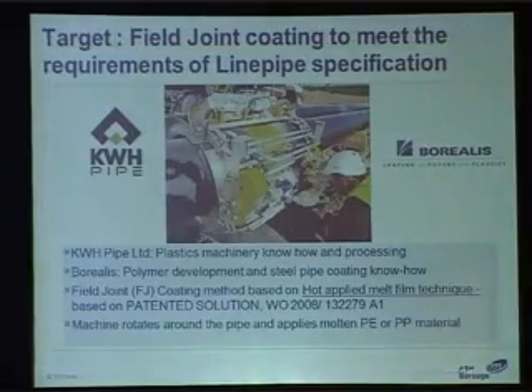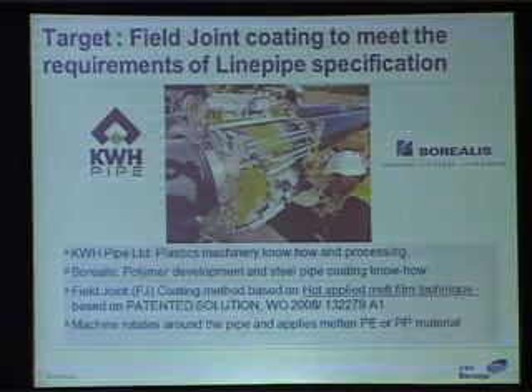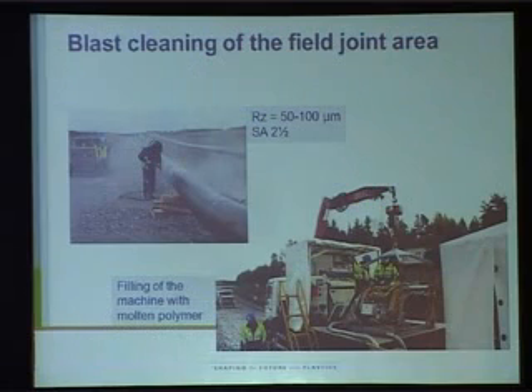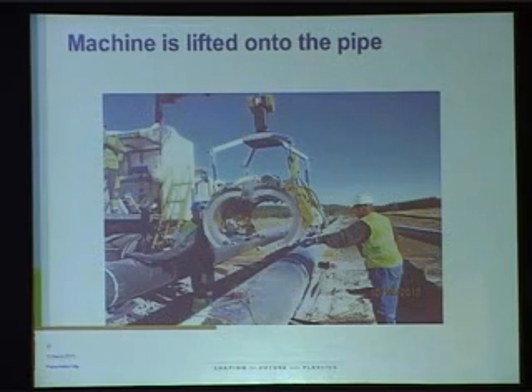This has been made possible by a collaboration between a machinery manufacturer and a coating raw material producer. Together, they developed a machine that can rotate around the welded joint and apply reactive polyethylene or polypropylene materials as a molten film on the FBE and also on the cutback area within the intercoating time, as is done in a factory applied coating. This system moves in a small truck parallel to the pipeline route. After welding of the pipeline, the joint area is blast cleaned to required roughness, while the machine is refilled with molten polymer from an extruder on board the truck. The machine is lifted onto the welded area of the pipe and locked in with a clamp system. For smooth movement of the machine around the pipe, it is designed in such a way that the center of gravity of the machine coincides with the pipe axis.